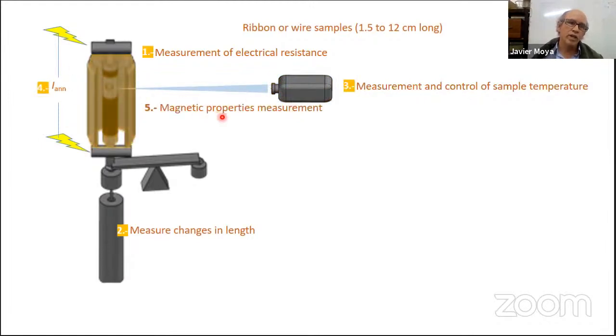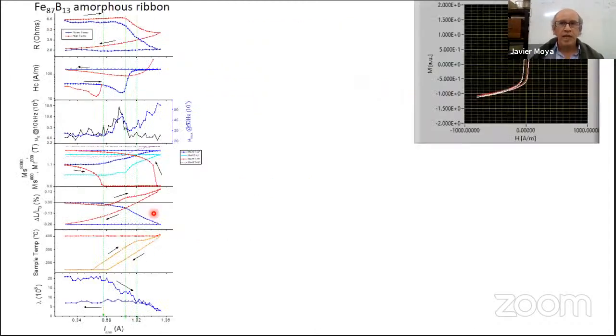And with this set of coils, we obtain the magnetic properties, and with this counterbalance beam, we induce stresses or not into the sample. So we can make stress analysis and magnetic field analysis on the samples. With this device, we are able to obtain the results in this figure simultaneously. In the first graph, we have measures of the electrical resistance as a function of the annealing current. The red curves show the resistance variation at high temperature, while the blue one indicates the measured value of the electrical resistance after the material has been annealed to the indicated current.